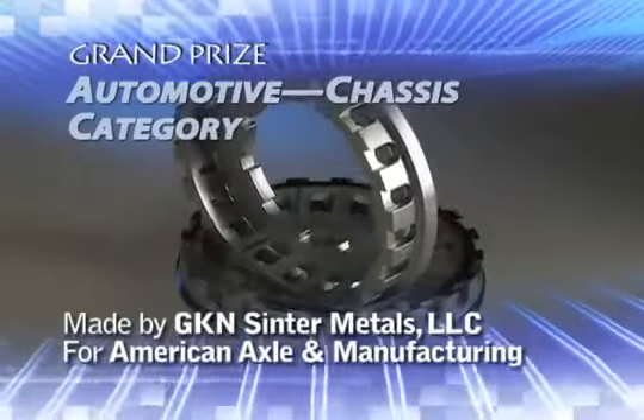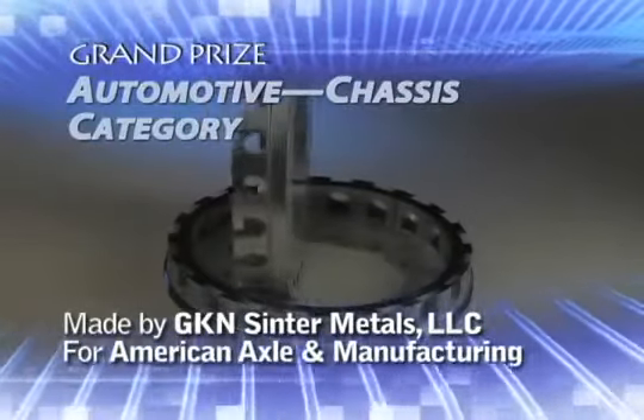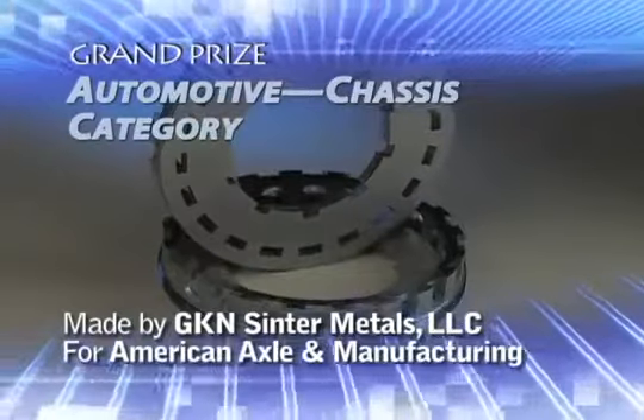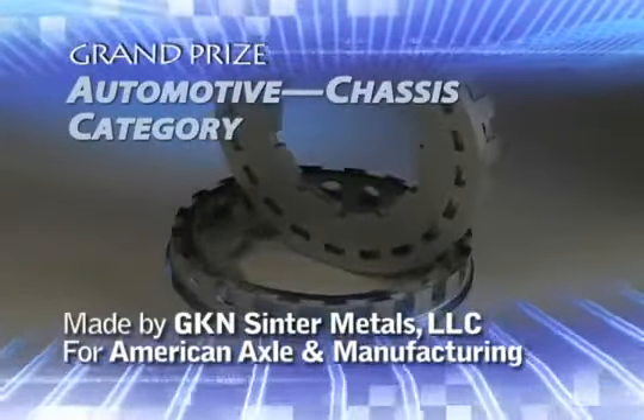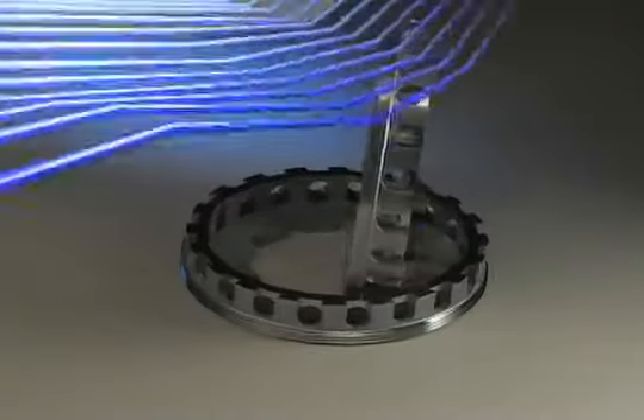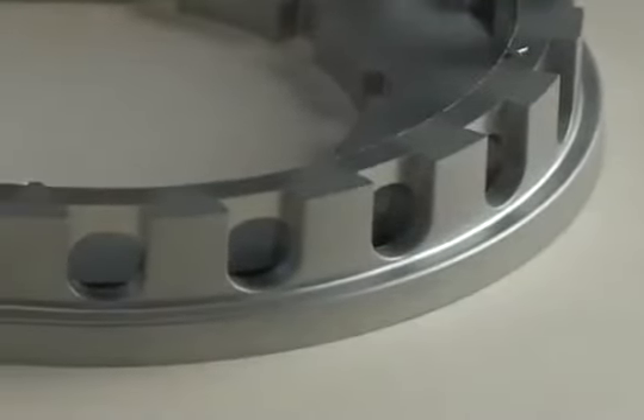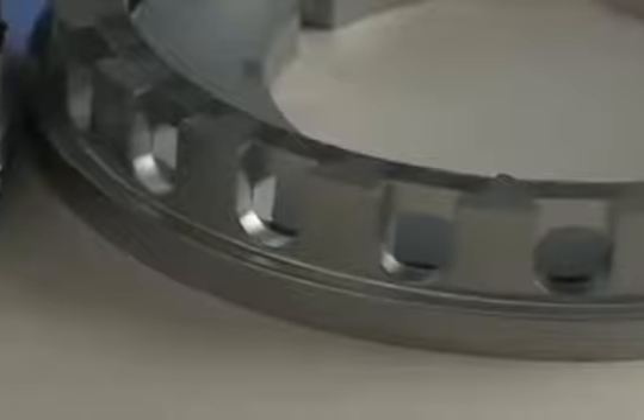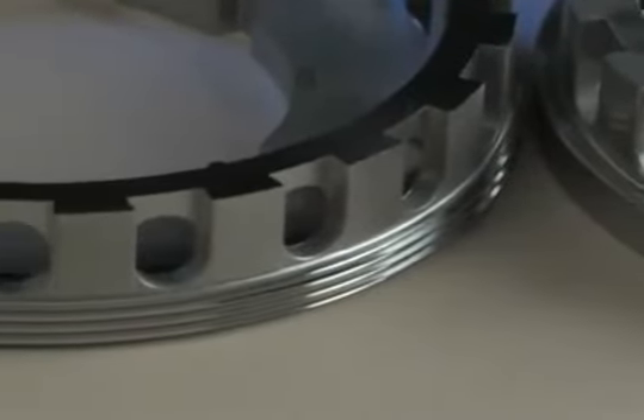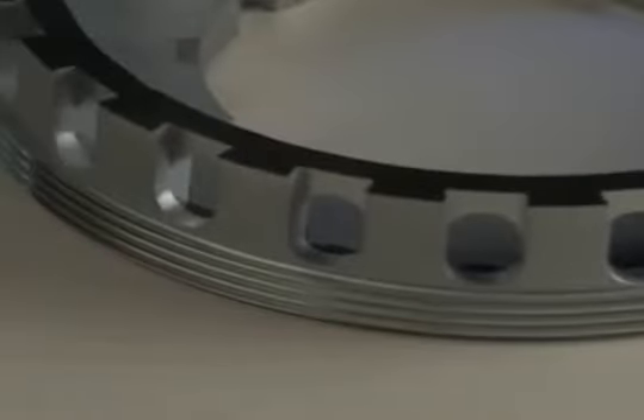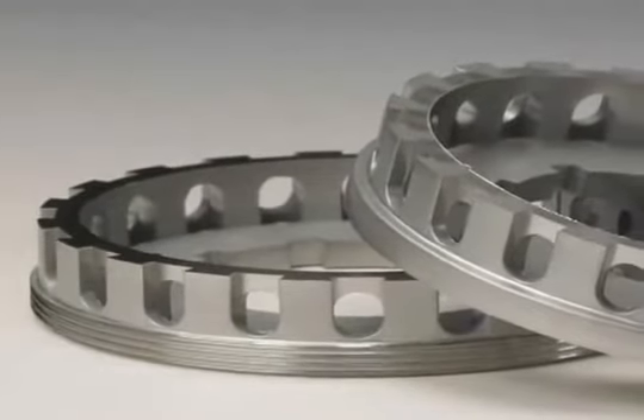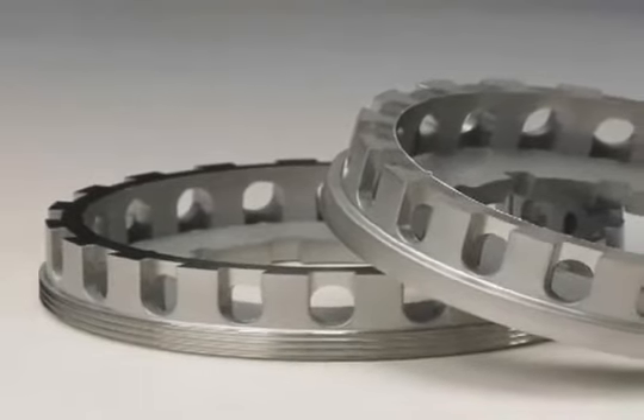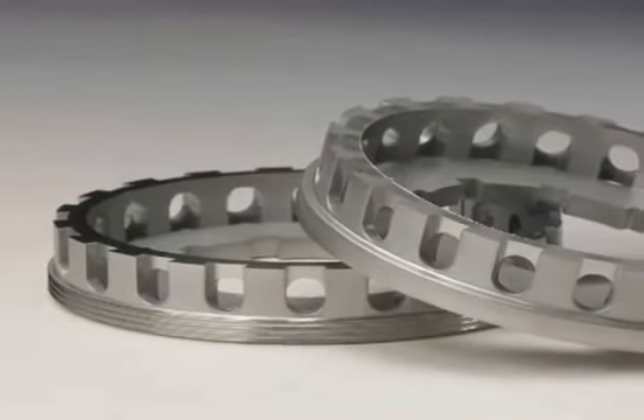GKN Sinter Metals LLC has also been awarded a grand prize in the automotive chassis category for a differential bearing adjuster made for its customer, American Axle and Manufacturing, and used in the GMT 900 rear differential on GM Tahoe and Yukon models. The diffusion alloyed PM steel part preloads the bearing and is locked in place through the side holes. Formed to a density of 6.8 grams per cubic centimeter, it has a 155,000 psi transverse rupture strength, 79,000 psi tensile strength, yield strength of 63,000 psi, and 90 HRB apparent hardness. A special die and dual upper punch design form the cross holes during compaction.